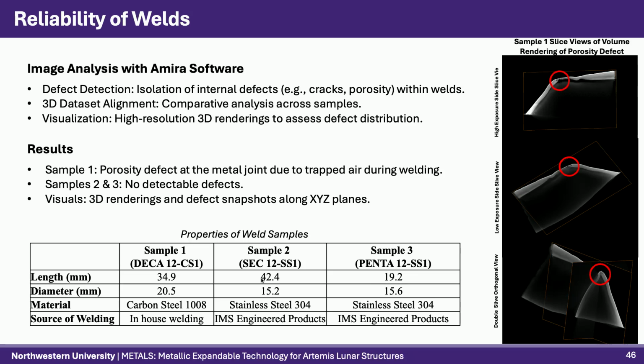This highlights the risks of inexperienced welding, such as breaches under pressure or void-induced stresses. In contrast, samples 2 and 3 showed no detectable defects, suggesting that professional welds have greater consistency in their internal structure. Overall, high-quality welding is crucial for safety in extreme environments, and if it's done professionally, we expect the welds to be reliable.